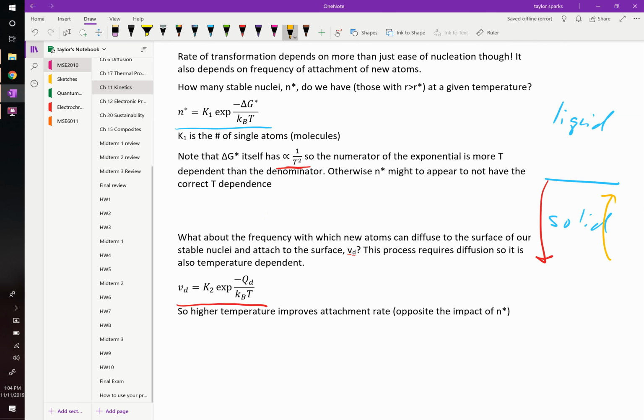So do you see there's a conflict setting up here? Your overall transformation is going to depend on one hand on V_D, but it's also going to depend on the number of nuclei that can grow. So it's the rate at which each nucleus is growing, and how many of them there are. And they depend on things differently with temperature. So you can see right away it's not like always higher temperatures are better or lower is better. There's going to be a sweet spot, a temperature at which you get your maximum transformation, because these two things have different temperature dependence. Can I answer any questions about that?